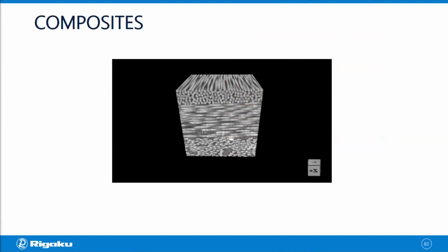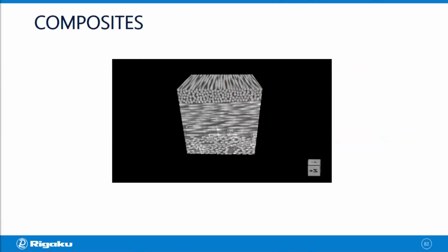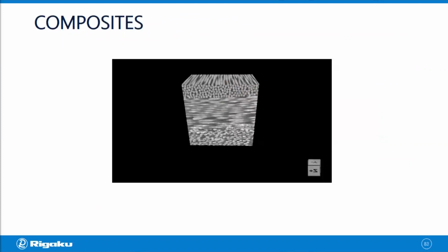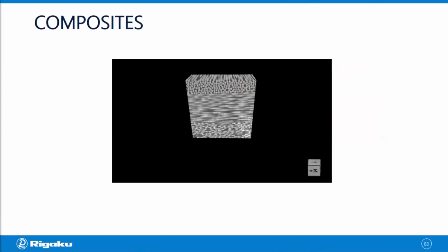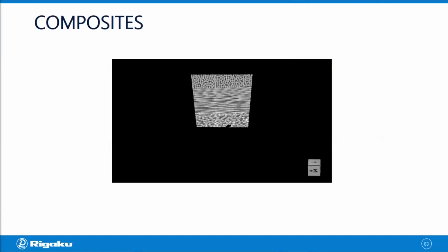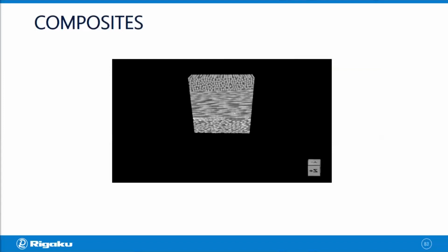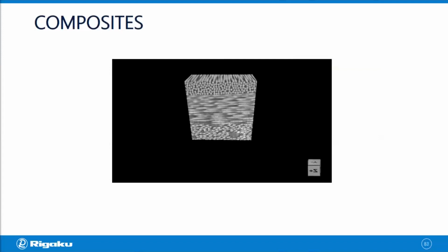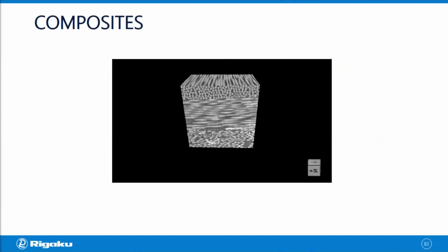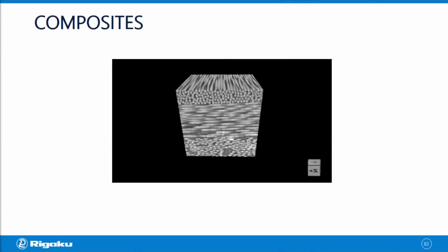This one is from a carbon fiber reinforced polymer. And not only that, you can see individual fibers, and they are about 7.5 microns in diameter. You can see packing density of the fibers. You can analyze the orientation of the fibers. And in this case, there are a couple of voids inside, so you can visualize the voids and color code them depending on their sizes.